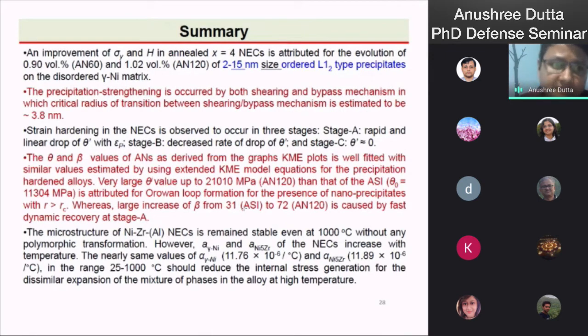In the summary of this chapter, the improved yield strength and hardness in annealed x equals 4 NEC is attributed to the evolution of 0.9 volume percent for AN60 and 1.02 volume percent for AN120 samples of 2 to 15 nanometer size ordered L1_2 type precipitates on the disordered gamma nickel matrix. The precipitation strengthening occurs by both shearing and bypass mechanisms, in which the critical radius of transition between shearing and bypass mechanism is estimated to be 3.8.